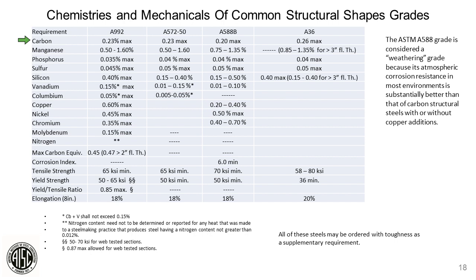We typically don't run in that range, but we're allowed to by spec. And then we'll bring it up. Typically, we like to get our strength from our microalloy additions instead of by carbon because we want to have a steel that has a satisfactory Charpy V-notch.